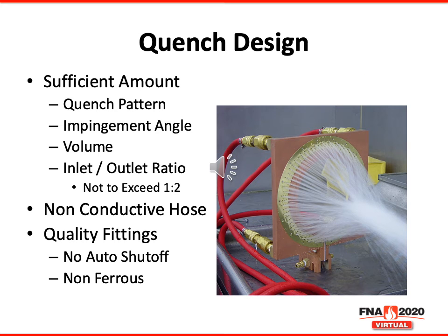Quenches should be designed to provide a sufficient amount of quench to fully transform the metallurgical structure as specified. The quench pattern should be a uniform array of holes to quench the part at a proper impingement angle. The volume of water required should be matched with a supply having an inlet to outlet ratio not to exceed 1 in to 2 out. Hoses should be specified non-conductive and rated to meet or exceed supplied water pressure. Fittings should be of high quality, non-ferrous, without shutoffs, which can clog and hinder quenching action.